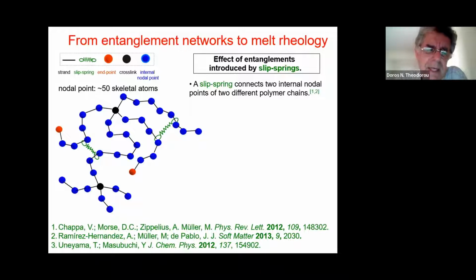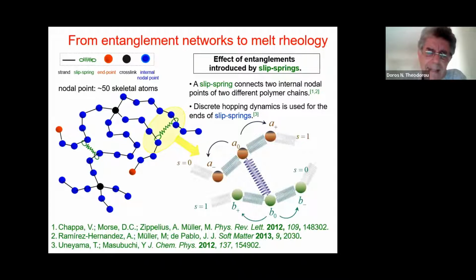A slip spring is a spring that connects 2 internal nodal points on 2 different polymer chains. And it is thought that each end of a slip spring can execute hops between adjacent beads along the chain, so the slip spring can slip along both the chains that it connects, and in this way it introduces an entanglement. Of course, we envision that this slippage process, this hopping process, is characterized by a rate constant. So we have to introduce a rate constant to describe the dynamics of these hops executed by the ends of the slip springs.